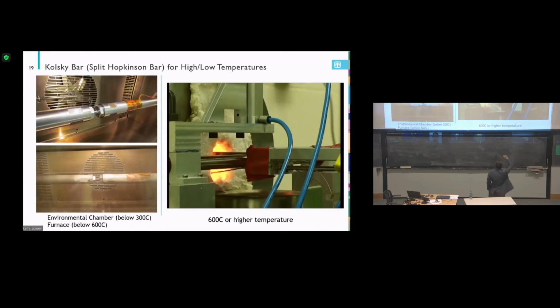So that's why we put the specimen into this big furnace for very high temperature. You can see we have the arm hold the sample heat there. When it's ready, we automatically pull the arm back, then put the sample between these two long rods, the Hopkinson bars. But at this time, the Hopkinson bars are still at room temperature and separated from the specimen.